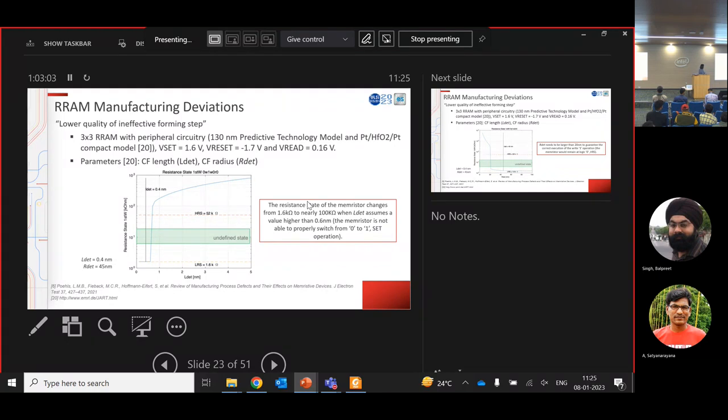So we changed these two parameters and tried to understand the impact on the functional behavior. Here is the LDET, the length of the conductive filament. The nominal value is 0.4 nanometer. Then you change this value and we try to understand the resistance state after performing a write operation. Here it's possible to see that from 1.6 kiloohms to 100 kiloohms, when